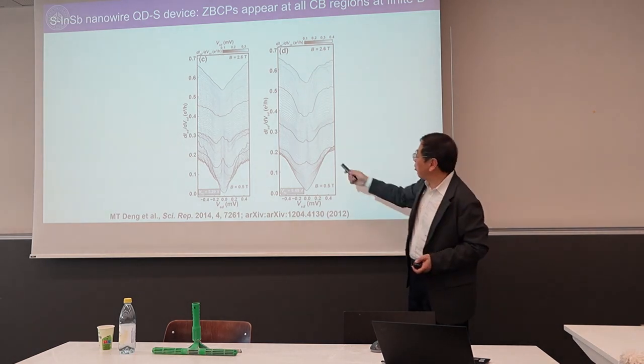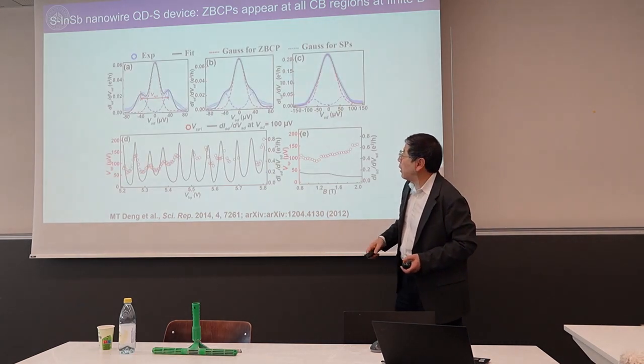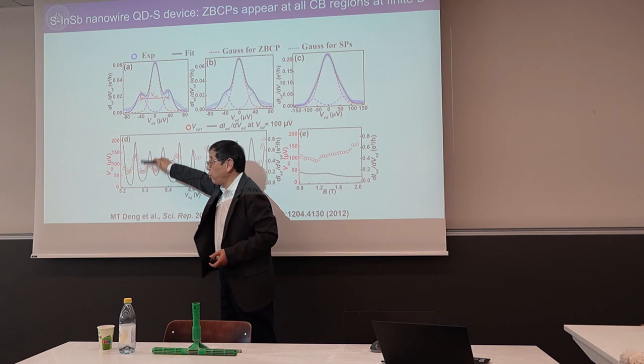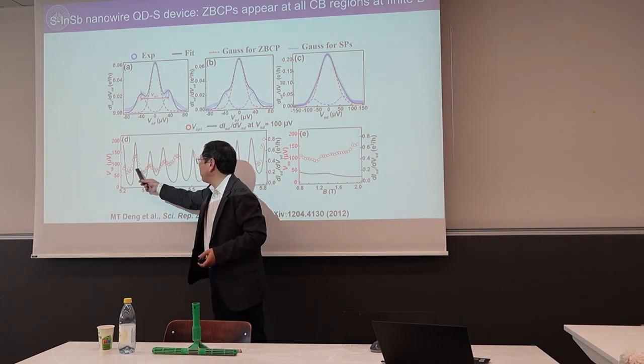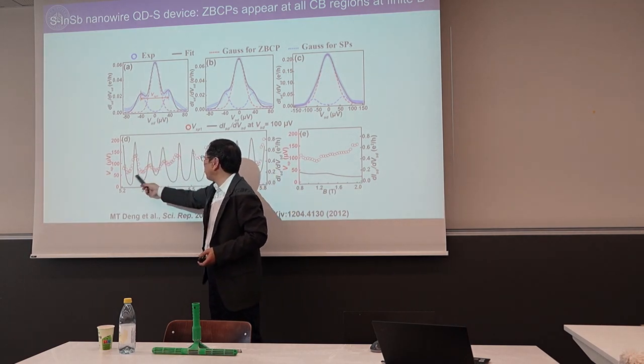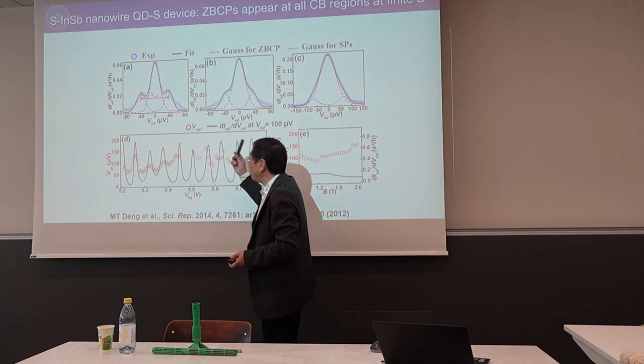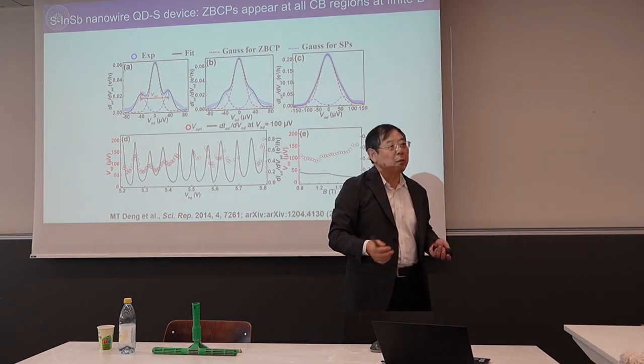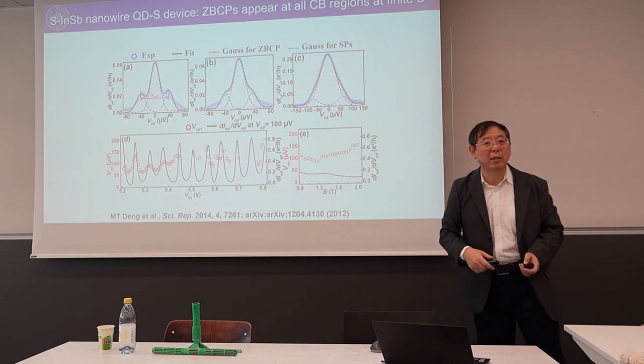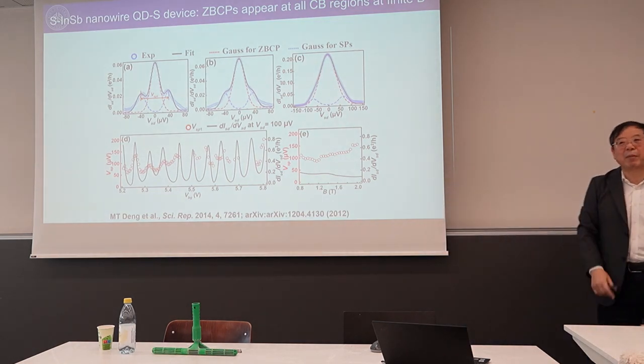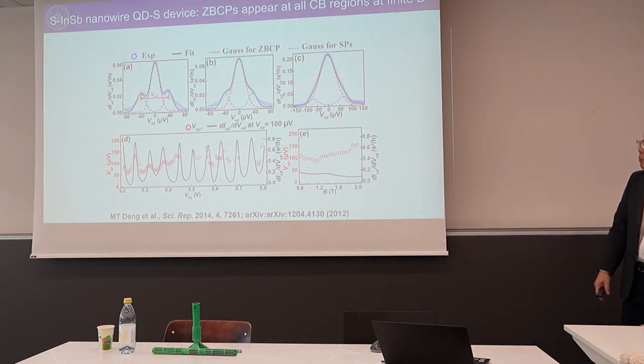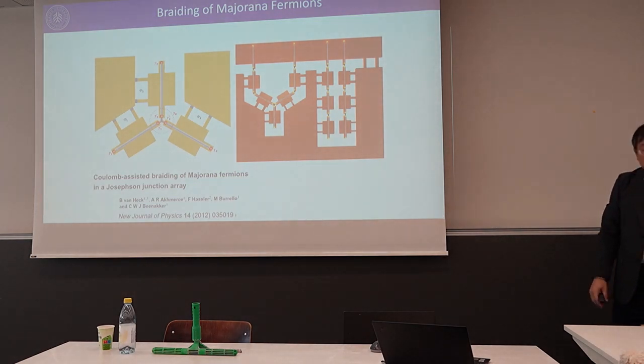We can characterize this triple peak structure together with the Coulomb oscillation of a quantum dot. You see the width of them. You can see the defined width of them really coincides with the Coulomb correlation, which proves the theory right. So that gives some signature of Majorana. So we also see some signature of Majorana. Okay, this is not enough.